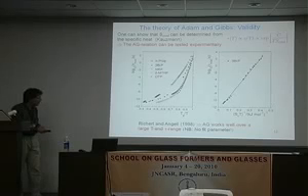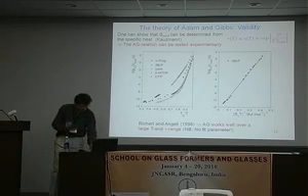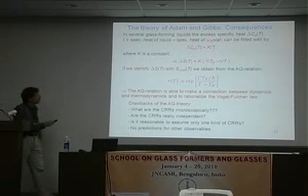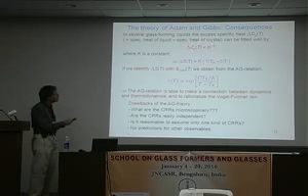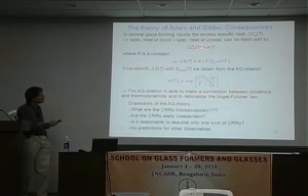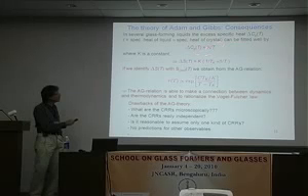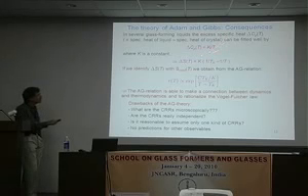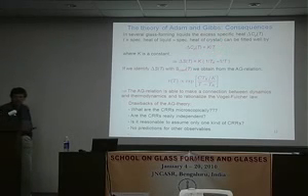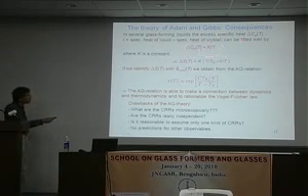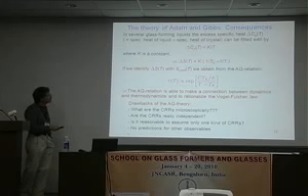Okay, so seems to be okay. So it's not the end of the story yet, because you can get out even a little bit more from Adam-Gibbs. So experimentally, not for all systems, but for quite a few systems, one finds that the excess specific heat capacity is given by a hyperbolic law. That is to say, it's a constant divided by temperature. This was also data by Alba Simonesco, Angel, and others that showed that this here for quite a few systems is a fair approximation.